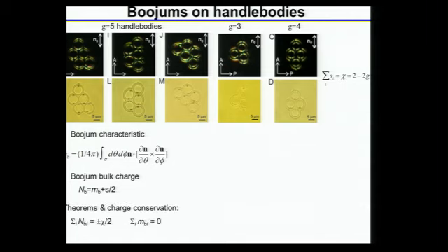Indeed, not only do we satisfy this condition for the two-dimensional topological defects, but the bulk defects, which are equivalent to the bulk defects that we saw before induced by particles with perpendicular boundary conditions, also add up to chi over 2, for the same reasons as before, right?